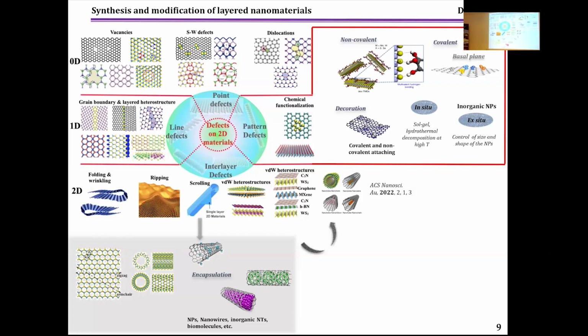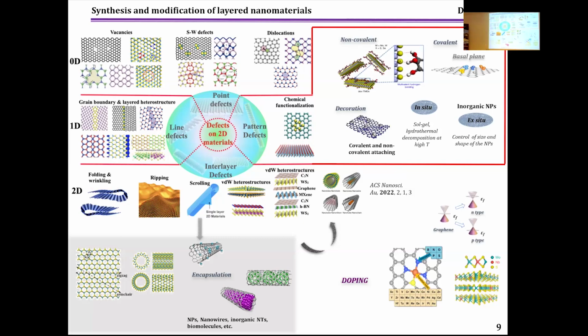Finally, which is also relevant and is nowadays being reported, is the formation of van der Waals heterostructures. These van der Waals heterostructures combine the properties of different inorganic systems, so we can tune the property of the material by the interaction of layers. We have different compositions. And finally, this heterostructure can also be formed inside one-dimensional systems. So doping, which is also relevant, includes the modification of the band gap of the structure by including dopant agents, which can be metal or non-metal atoms, in the structure of the systems.